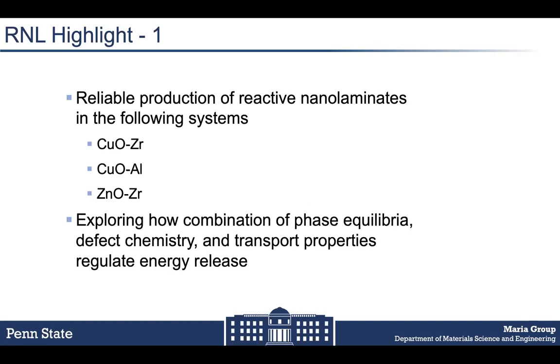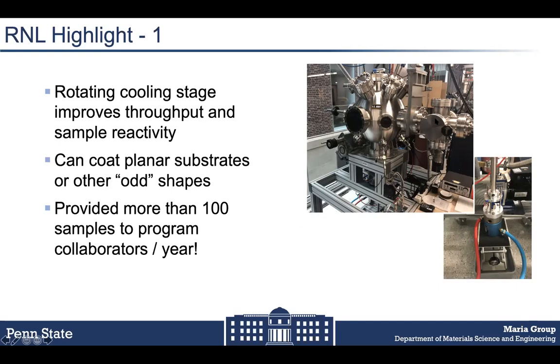So the system that we use to make these materials is shown here. It's a magnetron sputtering tool that currently has four sources. And one of the things that it offers is a cooling stage, so we can keep these materials quite cold to avoid reactions that would otherwise occur because of the heat that is unavoidable during sputter deposition. And we've engineered a stage that actually rotates while it has cooling water so that we can expand the number of materials